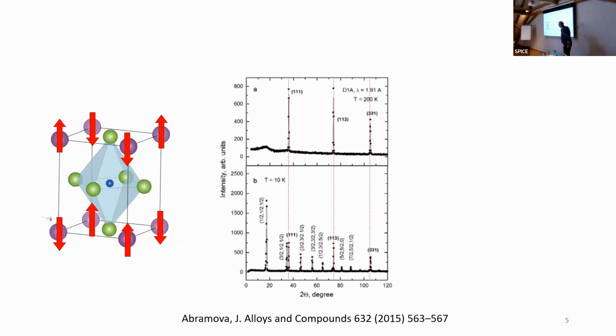Here's another example of this, which I think is a little more telling. This is a different material, it doesn't matter, where you see structural peaks, and then below the Néel temperature, you see these huge additional peaks, which we use to then solve the spin structure. And an important detail, which will bite us later, is that these peaks are very much comparable in size to the intensities from the regular crystal lattice.